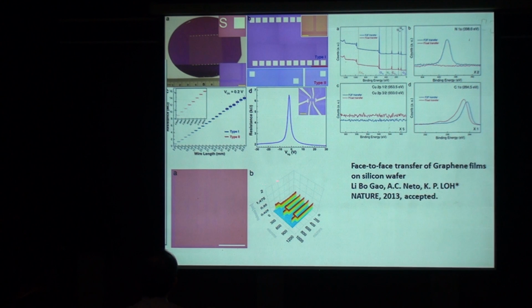So this transfer process allows us to grow large-scale 8-inch graphene wafer on silicon, and we can pattern very long lines, lines that are millimeter to centimeter long, and we find that the conductance is very good from this face-to-face transfer process.